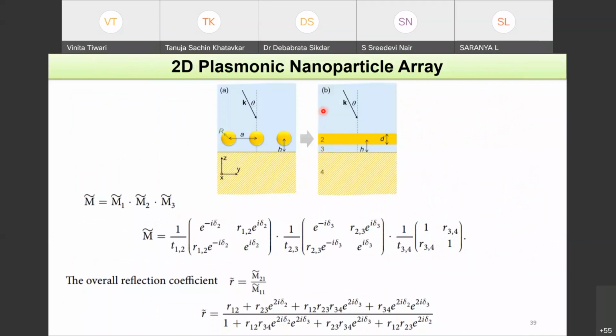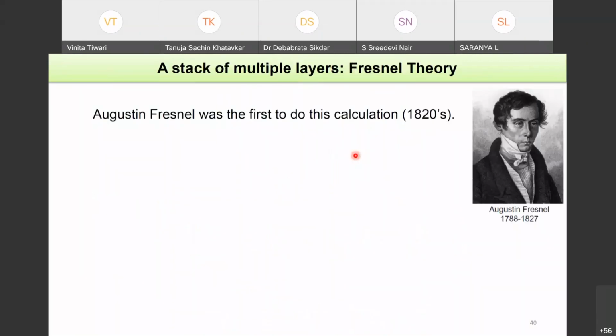And then you apply the transfer matrix method, where M1, M2, M3 are basically the different layers that are there. So each matrix will represent one interface, and that is how you can get an overall transfer matrix for this entire system. And once you obtain that overall transfer matrix, you can find out the element M21, and you divide it by M11. That will give you the reflection coefficient for this entire geometry. So this is how you can obtain the optical response, like reflection and transmission, from transfer matrix method and effective medium theory.